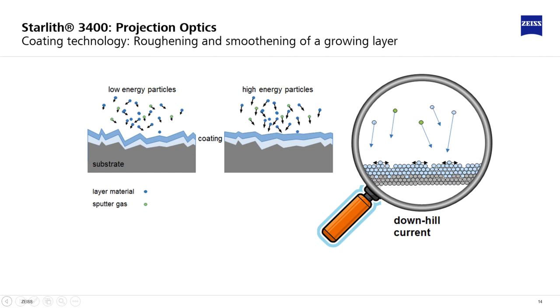Also, the roughness of the surface on which the multilayer is coated leads to a reduced reflectance. To reduce the surface roughness of the substrate, either the polishing can be improved or the rough substrate can be coated with a smoothing layer.